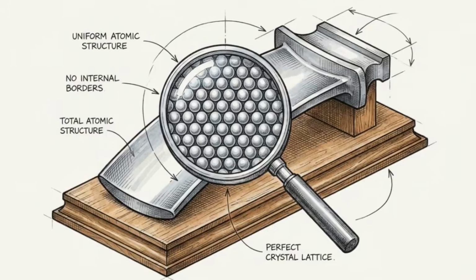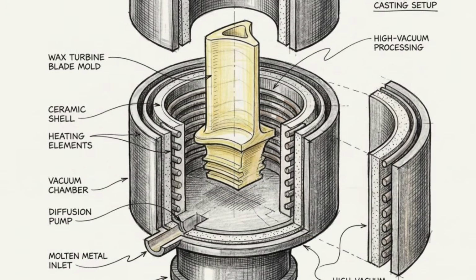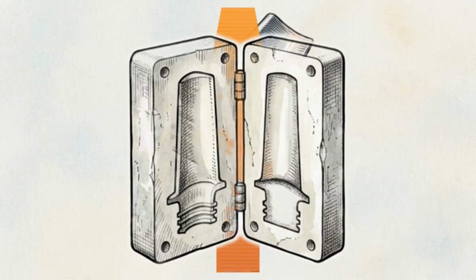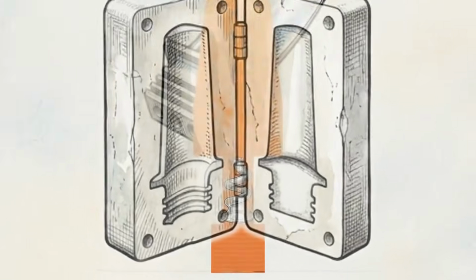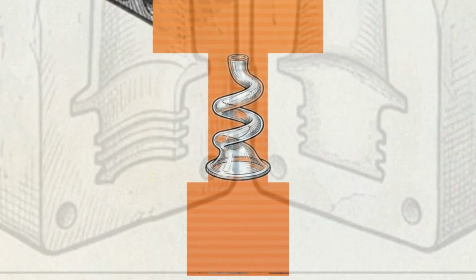They decided to cast the entire 300-gram turbine blade out of one single unbroken crystal, eliminating internal borders entirely. They start with a wax mold, which is filled with molten superalloy inside a furnace. The mold is then slowly pulled out of the heat from the bottom up, encouraging tall columns of crystals to grow vertically from a cooled base.